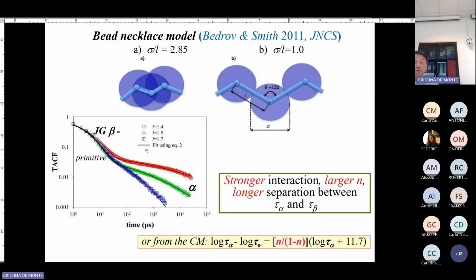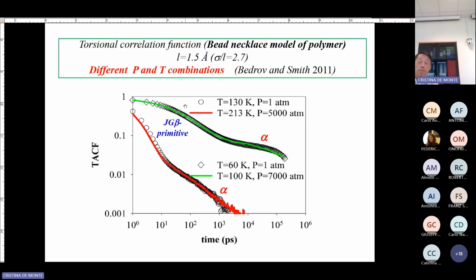Okay, now this is simulation. Very well done by Bedrov and Smith. They take this so-called chain, and then they put this together to have interaction by the Lennard-Jones potential. They found the beta relaxation, the alpha relaxation, and they also put pressure on it. This is simulation, but pressure, they can do it. This is different pressure. Beta, alpha, superpose perfectly in this case for this combination, and different combinations also superpose perfectly.